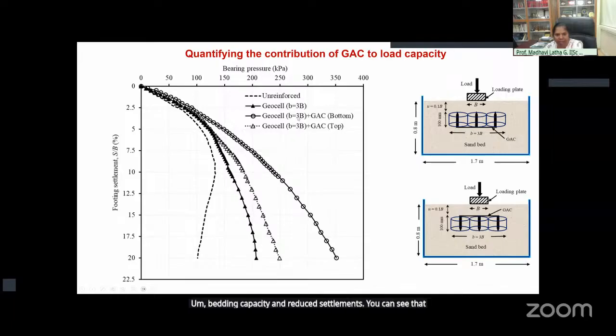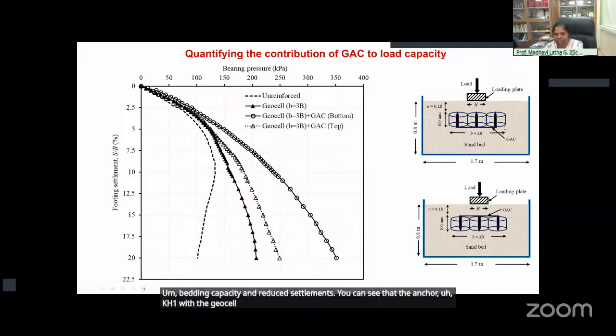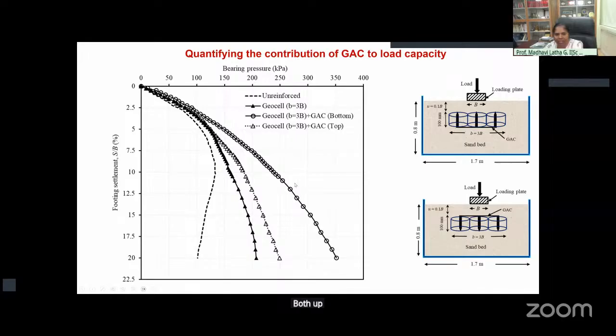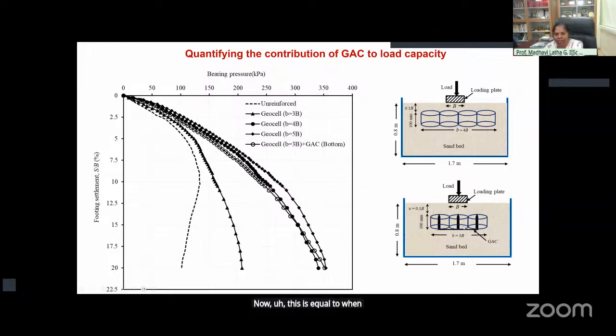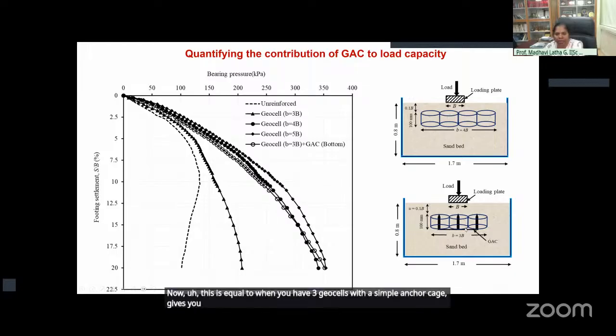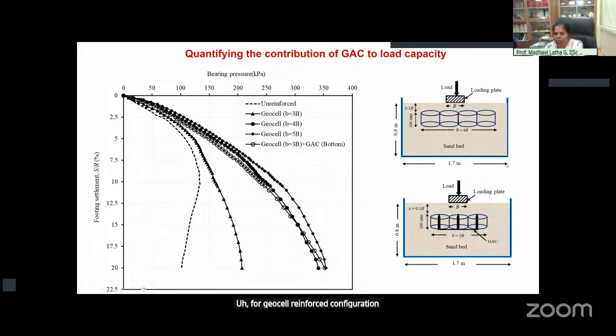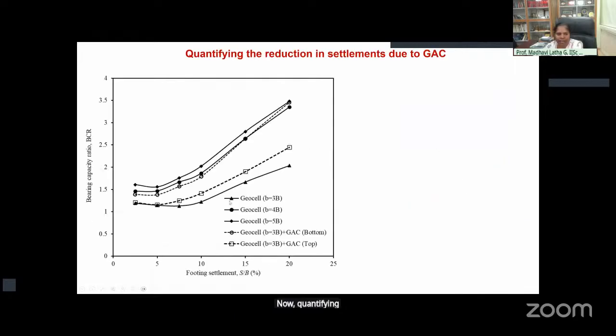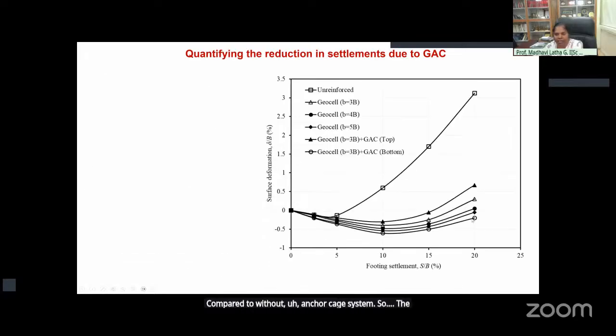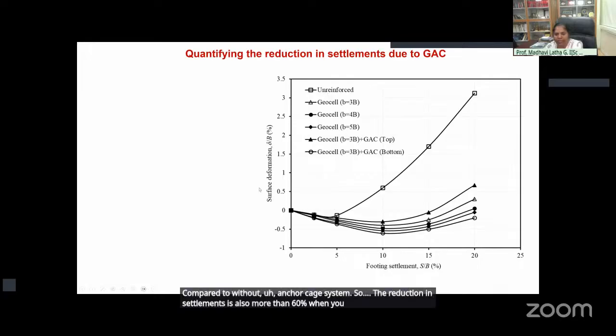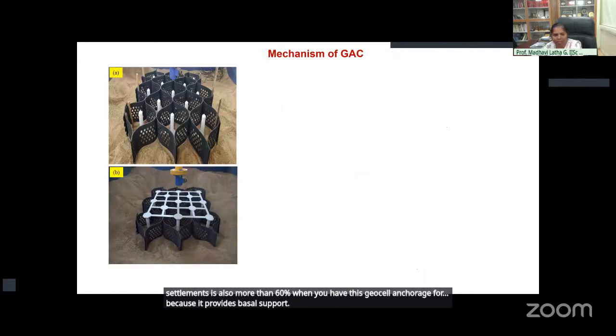You can see that the anchor cage with geocells up to 3 times the breadth of the foundation, both up and down configurations, the bottom one is much superior to the top down configuration. Now, this is equal to when you have 3 geocells with a simple anchor cage giving the same reinforcement benefit as a 4 geocell reinforced configuration, which gives so much savings in materials. Now, quantifying the bearing capacity ratio, you have almost 2.75 to 3.5 bearing capacity ratio with geocell with anchor cage compared to without anchor cage system. The reduction in settlements is also more than 60% when you have this geocell anchor cage because it provides basal support, and also there is a mechanism which I'm going to explain now.